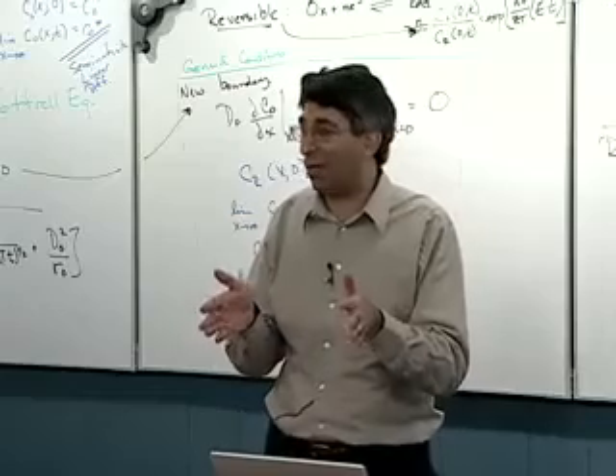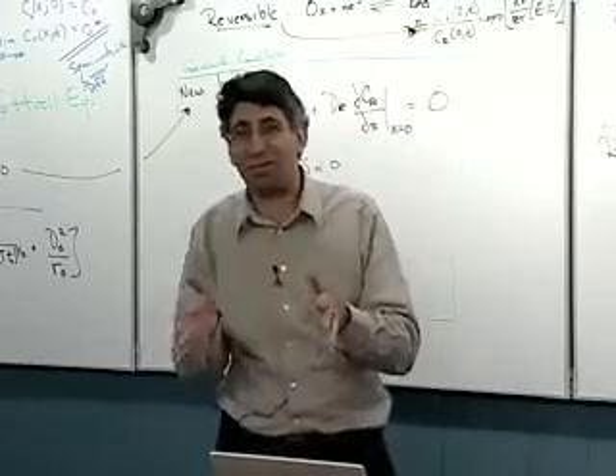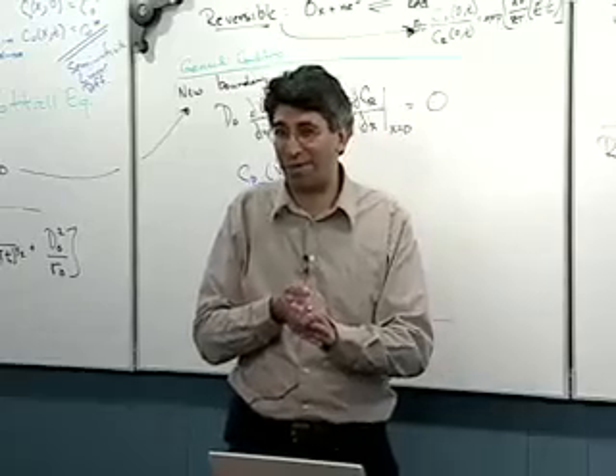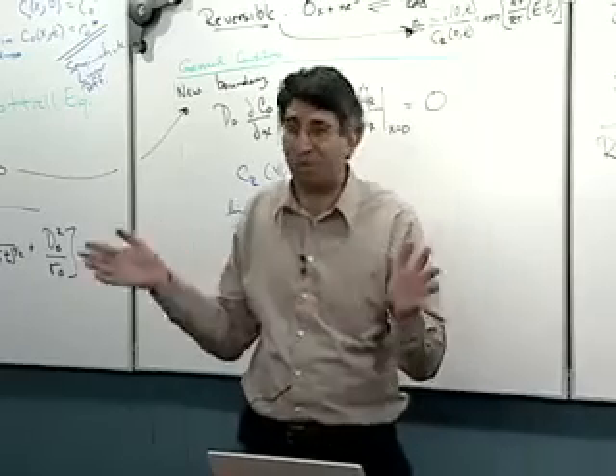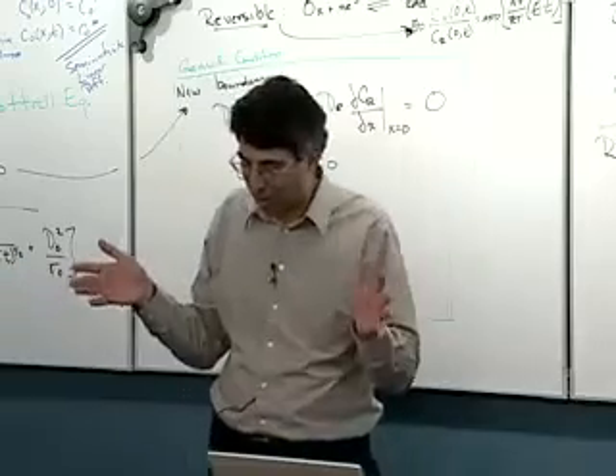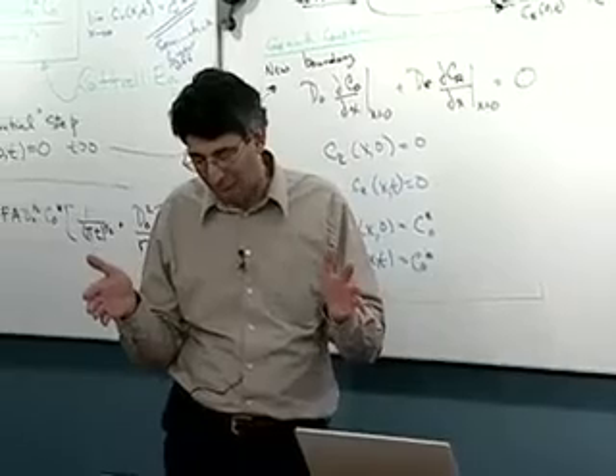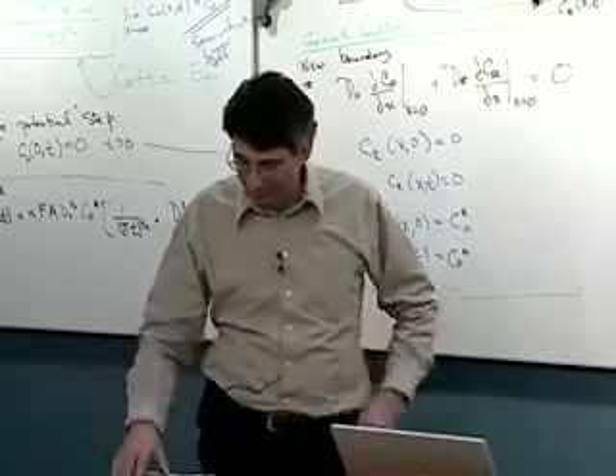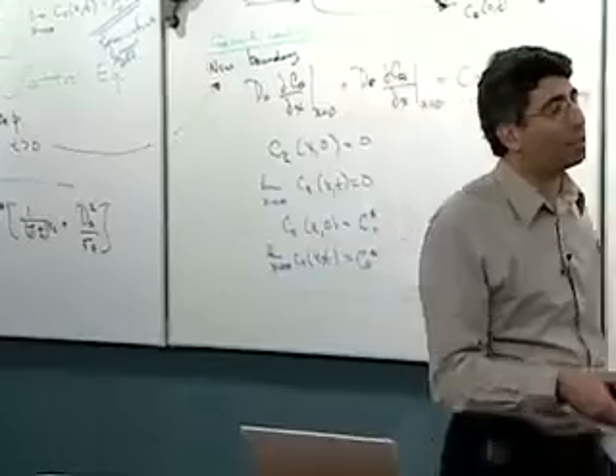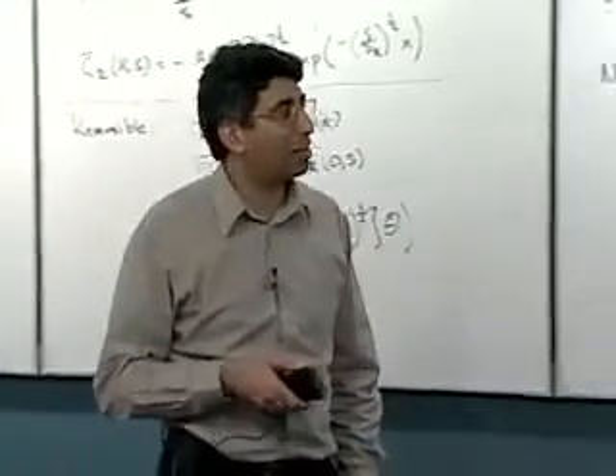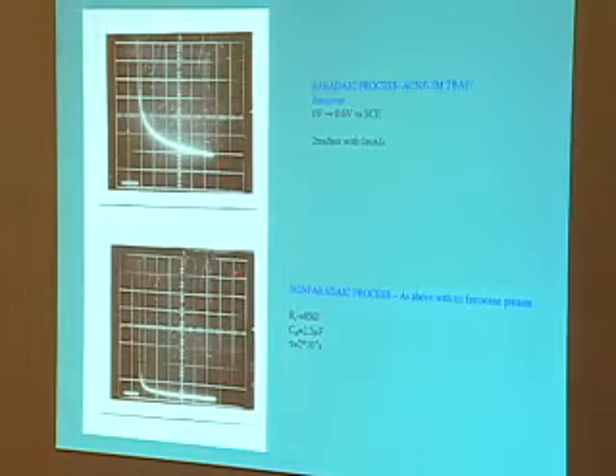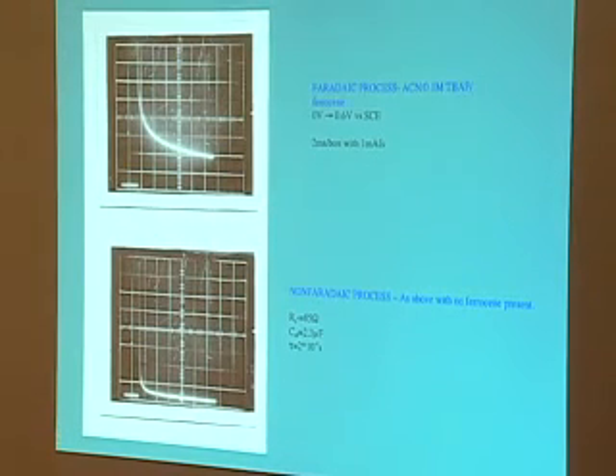you will get some other sort of convective process occurring in your cell if you simply wait long enough. Okay, you cannot avoid having vibrations, for example. You can have a vibration-free or relatively free environment for a short period of time, but it's not going to happen for a long period of time. So we saw on the one hand, because even under the best of circumstances, you have this RC time constant that's going to knock out the first couple milliseconds of your data. So we have no data for the first couple milliseconds that we can rely on without deconvolution.